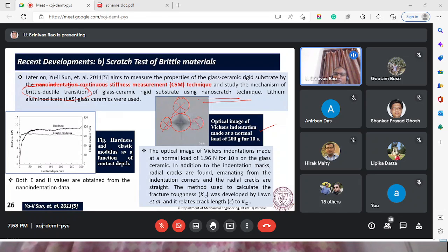These are basically cracks. That means the load is more than the threshold value, and so whatever depth we got is more than the threshold value. When we do this in a controlled way, it gives us the brittle-ductile transition. So the formula gives a basis, and then it can be found through experiments, through indentation tests or scratch tests.